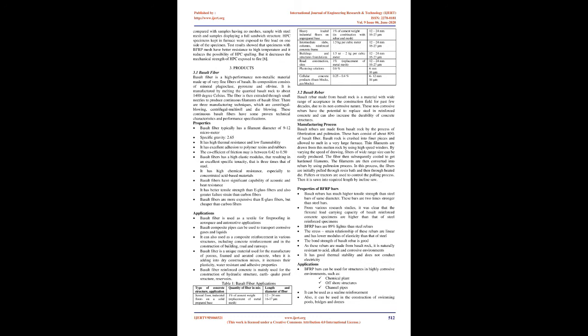4. Urbanski et al., 2013, identified the differences and limitations of basalt rebar in concrete structures in relation to steel reinforcement. In this study, the deflection and crack pattern of simply supported basalt reinforced beams and steel reinforced beams were compared. It was found that the failure of the basalt reinforced beam did not occur suddenly and it has significantly higher deflection compared with the steel reinforced beam due to the lower modulus of BFRP bars. Also, the average crack width is 3 to 4 times higher than in the steel reinforced beam. This study also points out that deflection and crack width are the major factors to be considered in the design of basalt reinforced concrete beams.